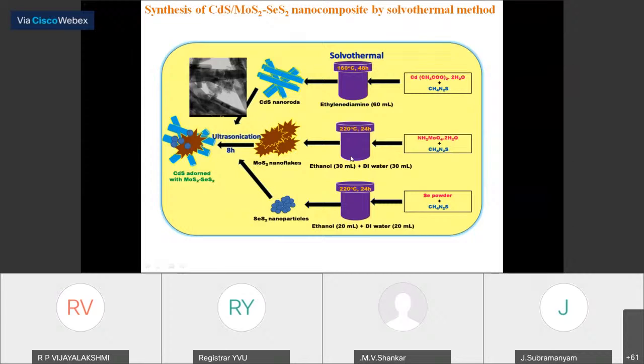Then we synthesize the selenium sulfide. The selenium sulfide is also synthesized by using the solvothermal method only. So in this one we obtain this type of structure by using the selenium sulfide. So we have the molybdenum sulfide, we have the cadmium sulfide. We have three products, that means three compounds we obtained by using the solvothermal method. So we have used two different size autoclaves to obtain this structure.